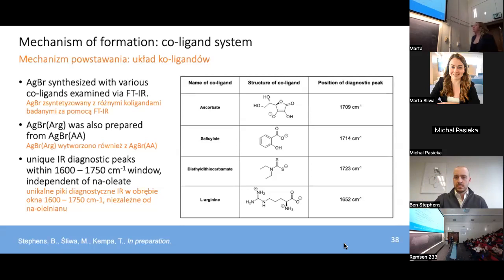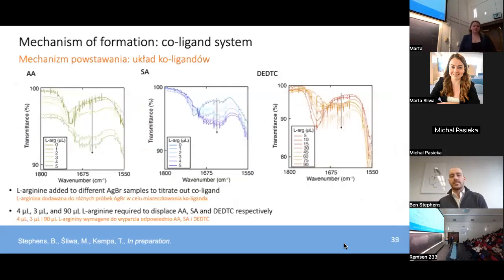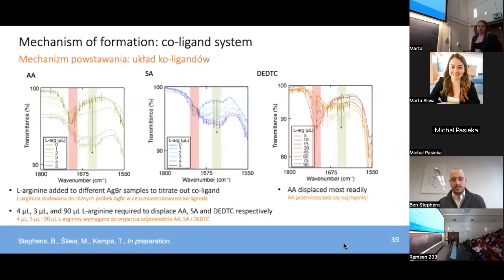We use this technique because thankfully all of these co-ligands have diagnostic peaks that are very far away from the oleate molecules that are in excess in the solution. So it was easy for us to be able to track their presence as well as their disappearance using this method. So using FTIR spectroscopy, we can visibly track the displacement of the co-ligands when we introduce L-arginine into the solution. Specifically, we monitor the growth of the FTIR peak that corresponds to the L-arginine here at 1652 wave numbers roughly, as well as the concurrent disappearance of the FTIR peaks corresponding to those ascorbic acid, salicylic acid, and carbamate ligands, respectively.